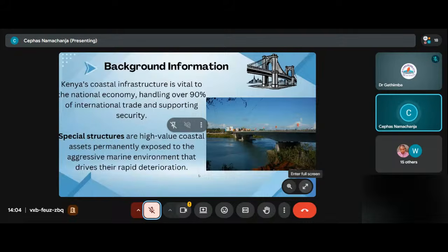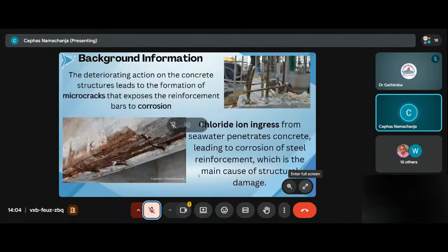The coastline of Kenya houses critical infrastructure that facilitates over 90% of the country's international trade. Special structures such as dams, piers, bridges, quay walls, and water tanks are exposed to a harsh, aggressive environment, such as alternate cycles of wetting and drying, tidal action, and our focus, chloride action, which mainly leads to the deterioration of these structures from the formation of microcracks.